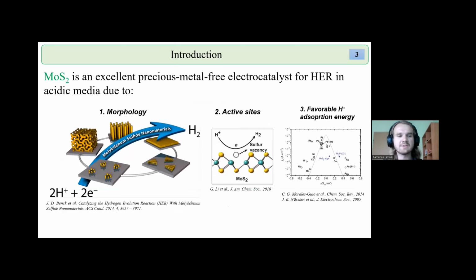The reason we use molybdenum sulfide is that it is a fairly versatile and functional material. It is a semiconductor. It can have various morphologies, which depend on the way in which the material was synthesized, and there are many ways to synthesize this material. In this study, it is mostly electrochemical, which I will talk about later. The material has an interesting structure, and in the structure, it has active sites, which are typically sulfur vacancies. And these vacancies have a favorable energy specifically to absorb hydrogen. And that is why this material is an excellent electrocatalyst for hydrogen evolution,